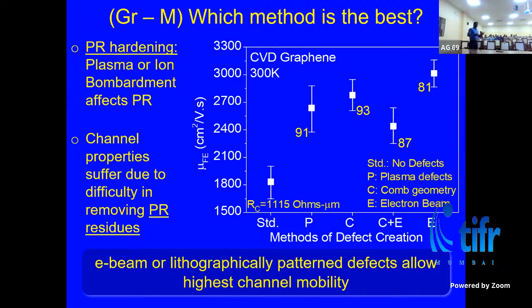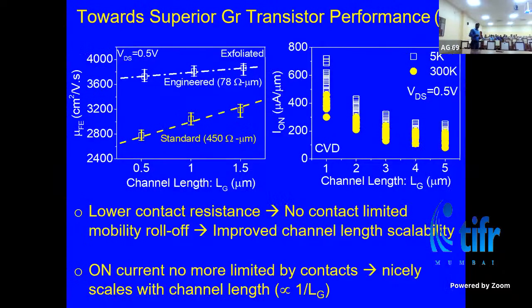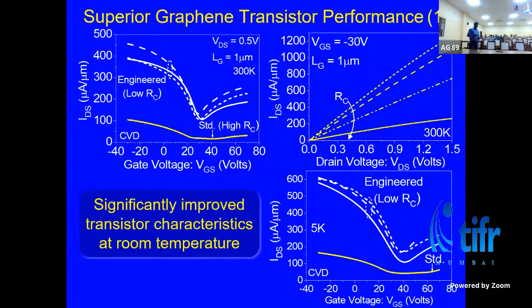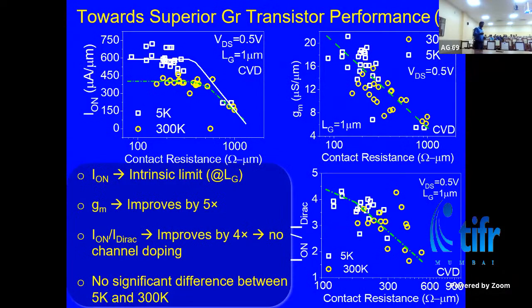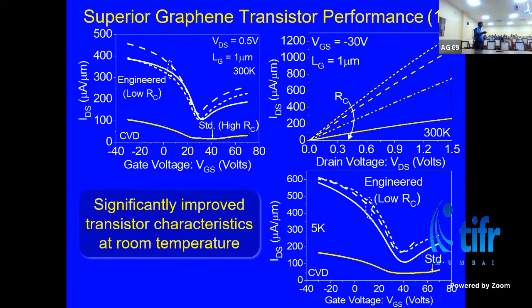Right. So let's skip some of these details, and I'll come to this. So now what you see is a comparison. This is the standard contact-based graphene transistor, where you see the Dirac point and the change in the current. Whereas you see the other one, which is the engineered contact, and you see more of a textbook-like IV characteristic of the graphene device with a very nice Dirac point being demonstrated and a significant improvement in the current from this point to this point. So there is a significant improvement in the I ON to I Dirac as the contact resistance reduces, as well as a significant boost in the current value of these devices for a given bias condition.